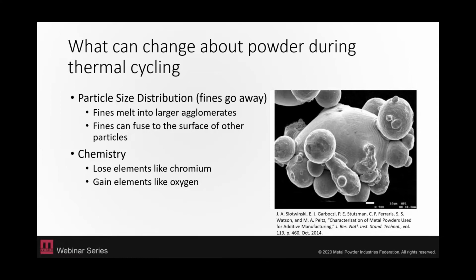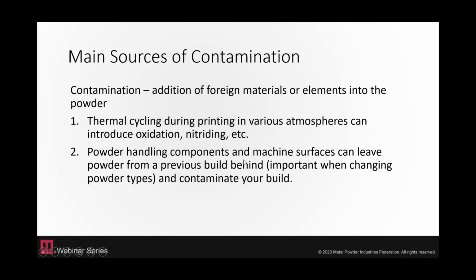So those are the major things happening in the powder bed fusion processes that you're really not going to see in a typical powder metal process, because you're not repeatedly thermally cycling your powder bed that you're using for the next build. There is actually a new electron beam system on the street that doesn't sinter the powder just for this reason. So that's kind of the progression of the technologies. They're getting away from that sintering.